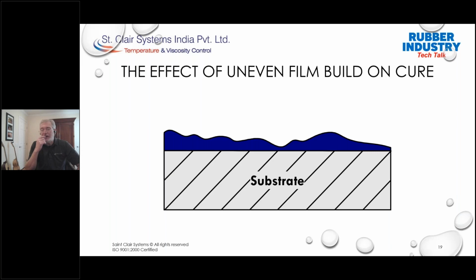This can have a significant impact on our film cure. As we can see, the thinner film areas are going to cure more rapidly than the thicker film areas, and that makes perfect sense. The uneven surface will also have a negative impact on our bond performance. It's also possible to create blisters from solvent entrapment under the cured surface of the coating. As it cures, the solvent gets trapped and blisters form as that solvent tries to evaporate up through that sealed surface. And this has a negative impact on bond performance in the